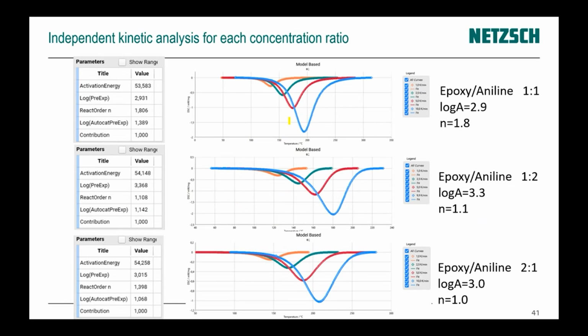Now we can make some preliminary analysis of each ratio of reactants, and we can find that the activation energy everywhere is the same. It depends on the nature of the reacting materials, but the pre-exponential factor is totally different, and the reaction order is also different. It is from 1.0 to 1.8. It is almost twice higher, and here we have 1.1.